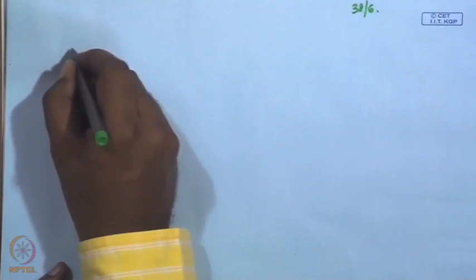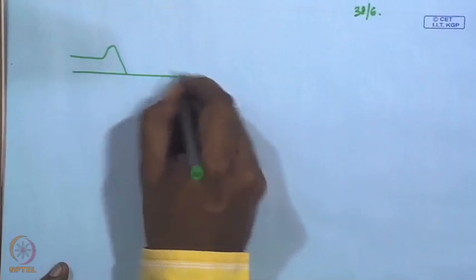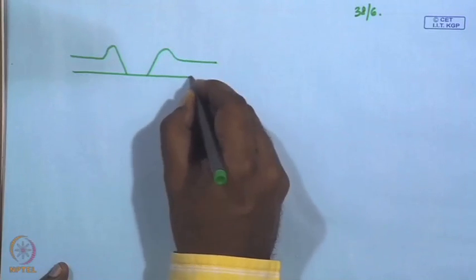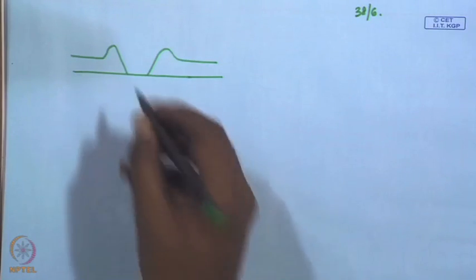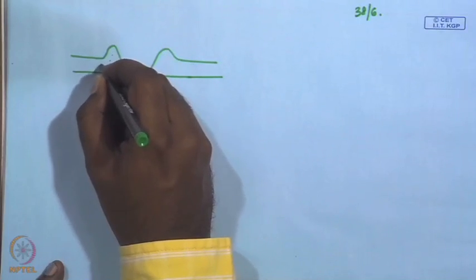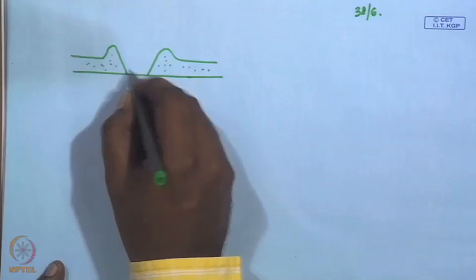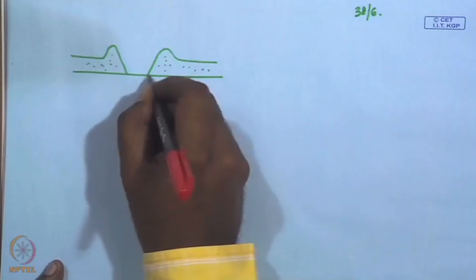As has already been pointed out, these particles preferentially stayed within the polymer. So, as the polymer film ruptured and the hole started to grow, the particles also were there within the film, and there was no trace of particle in the ruptured zone of the hole.